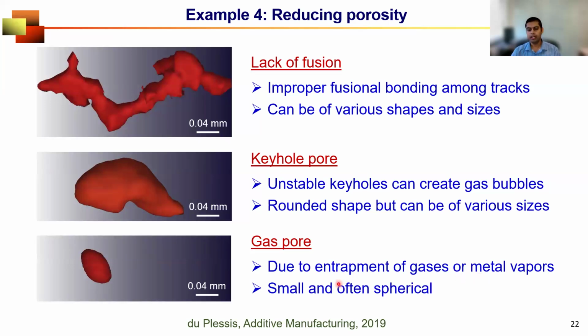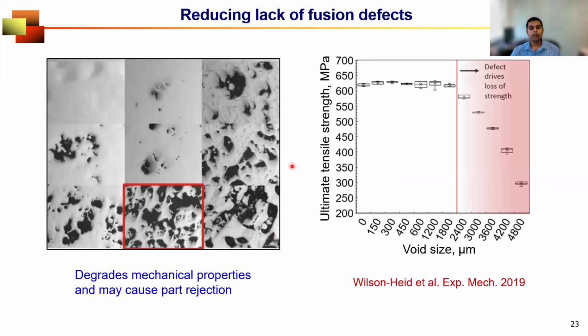within the molten region and create porosity. You can see they vary widely in terms of their shape, size, and morphology. So here I'm going to talk about lack of fusion and gas porosity. Like all three types of porosity defects, the lack of fusion defect, which is represented by improper fusion among tracks, significantly deteriorates the mechanical properties. As you can see, the ultimate tensile strength decreases very rapidly with the size of the void.